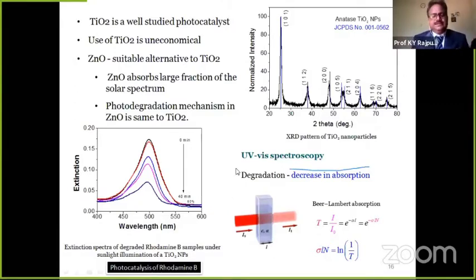So how to use this? TiO2 nanoparticles are taken and dispersed in the polluted water, and this polluted water is continuously stirred and kept under a light source, or you can keep it in sunlight. What you see here with respect to time is the extinction, the optical absorption taken in a spectroscopic experiment. At regular intervals, a sample is taken out and the spectrum is measured. It is seen that with respect to time, the intensity of this peak is decreasing. Therefore, this TiO2 acts as a photocatalyst. This is the idea.